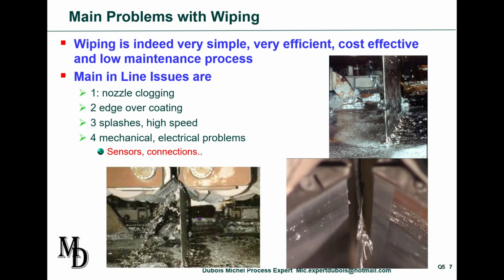This describes, for example, a typical splashing issue that occurs over certain line speeds. I published a lot of this. This occurs when you are running 180. Here is typically what could happen on the edges. And here are a lot of splashes and so on with the flow here on the zinc layer on the pot that could be different on each side.